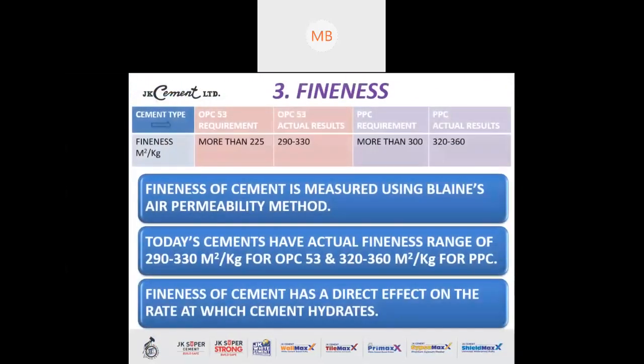Now the third and very important point is the fineness. The fineness of cement has a direct impact on the water requirement of the cement paste. The finer the cement, the more will be the water requirement, because the surface area is increasing, and vice versa. So we need to have an optimum fineness in cement. Fineness is measured in meter square per kg. The OPC 53 requirement is more than 225 meter square per kg. OPC 53 actual result range is between 290 to 330 meter square per kg in India.